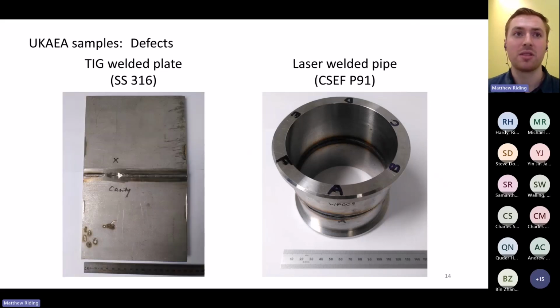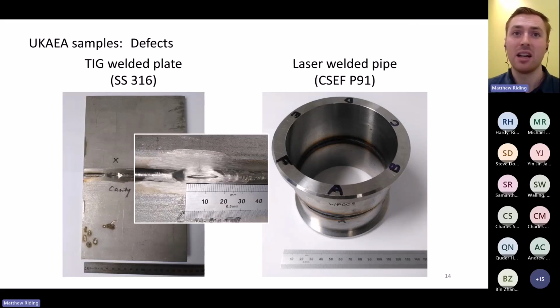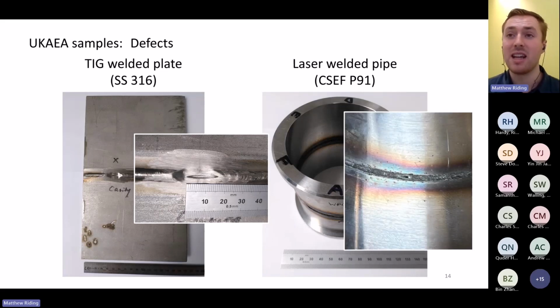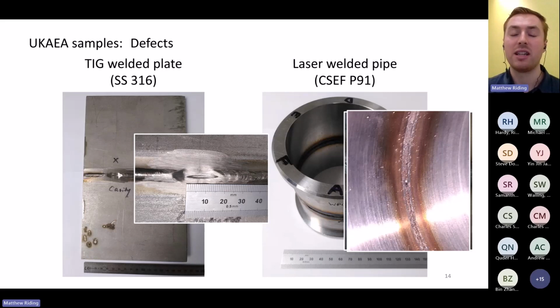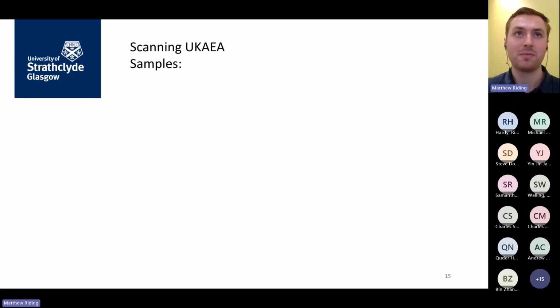And both of these samples contain defects. The plate has an artificial defect in the root of the weld, and the pipe contains a naturally formed keyhole type defect at the end of the laser welding process. So we went hunting for those defects and tried to demonstrate a detection of both in these samples.